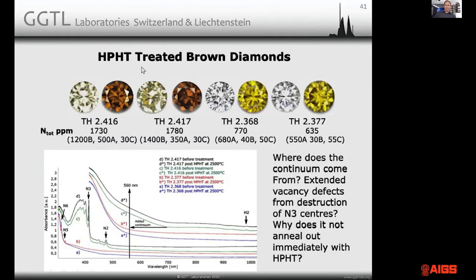You can get brown diamonds by HPHT treatment. What we have done here, we have taken Cape diamonds. Some of them were perfectly colorless, and some of them were yellowish Cape diamonds with very high nitrogen content, typical Cape diamonds, and we have submitted them to HPHT treatment at about 2,500 degrees, so very, very high temperature. And actually the colorless stones, as you can see in the spectrum down here, have no A and B, they have no N2, no N3 center absorption because they were actually D color.